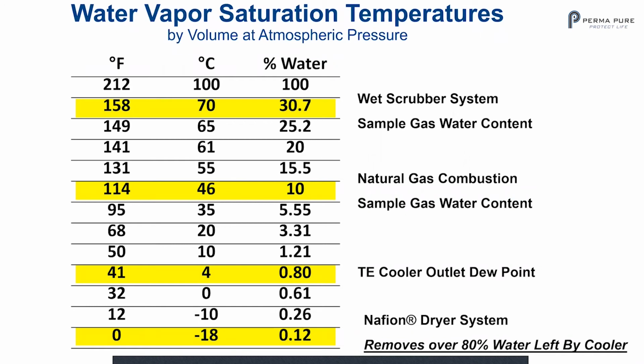That's typical. And look at the bottom there. A Nafion dryer system, typically at minus 18 degrees C dew point, will get you a percent water of 0.12, removing over 80% of the water left by the cooler. This is one of the reasons why you have so much less problems with your analyzer and much less analyzer maintenance, because we don't have that water vapor in the sample gas that's going to recombine with the components that we're looking to measure to create acids.